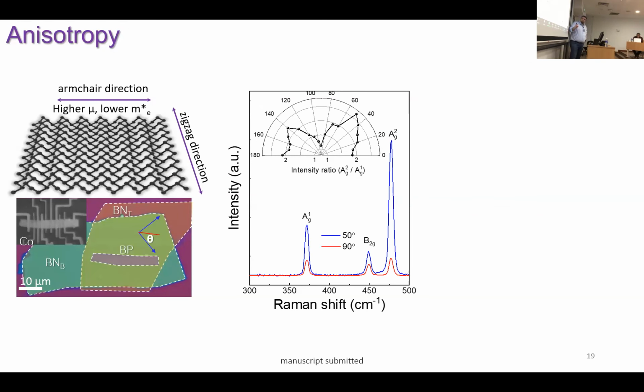Okay, so now I will also be talking briefly about our work on anisotropy. As I mentioned, this material has a puckered structure. So it has edges along the armchair and also zigzag edges. I have listed just the keywords here. Along the armchair direction, if your spins are propagating, they have higher electronic mobilities, and effective masses are also smaller. Small effective mass also means small effective spin-orbit coupling strength, right? And along the zigzag direction, the mobilities are lower, and the effective mass is also higher. So then the spin-orbit coupling would be different. As a result, you would expect some direction-dependent spin transport in this material.